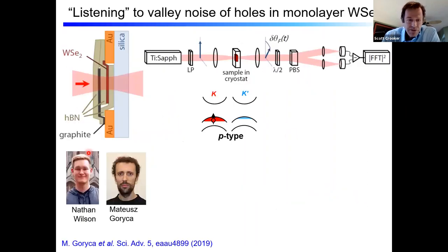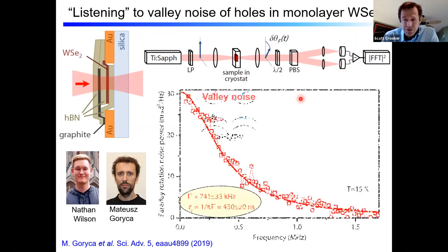We did this in very close collaboration with the group of Xiaodong Xu at University of Washington, his student Nathan Wilson, and Mateusz was the postdoc here at the Magnet Lab who did the measurements. They built a very beautiful sample. It's a single monolayer of tungsten diselenide, and it's electrostatically gated. We have a laser tuned near to the relevant optical transitions, and valley fluctuations gave us Faraday rotation fluctuations, which we measured, again, using our spectrometer. And this is what they heard.